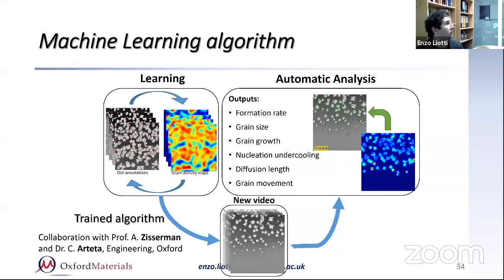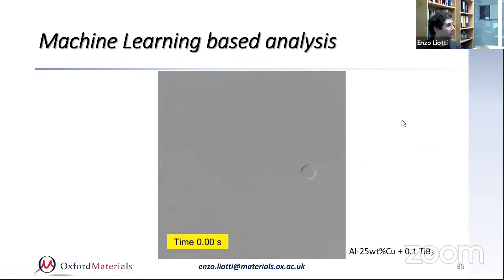Therefore, we worked with the computer vision group in engineering to develop a machine learning algorithm that was able to understand the images. So we trained on 6 videos out of the 140 we analyzed, and the algorithm was then capable of recognizing the grain in a new unseen video. And then we used that detection algorithm to attach a measurement algorithm. So once the grain were detected, another part of the algorithm was measuring automatically the grain size, the formation rate, grain growth, nucleation undercooling, diffusion length, grain movement and more. So here is an example of the algorithm at work.